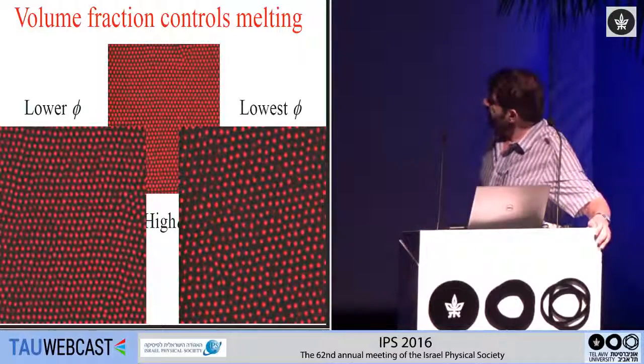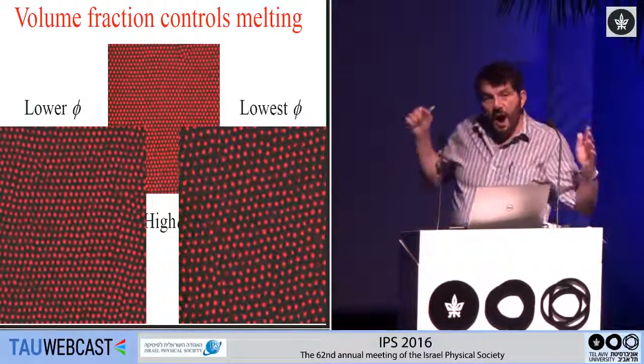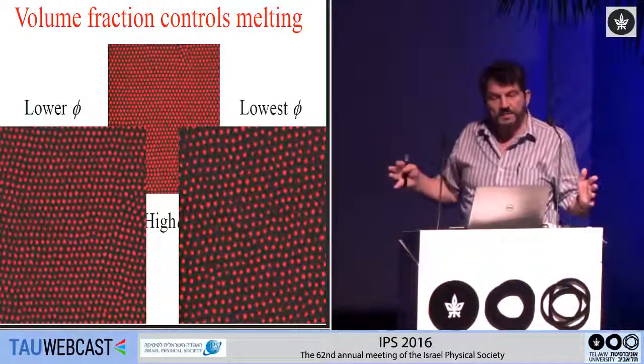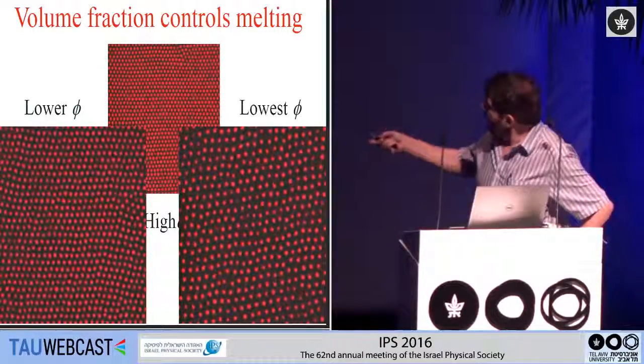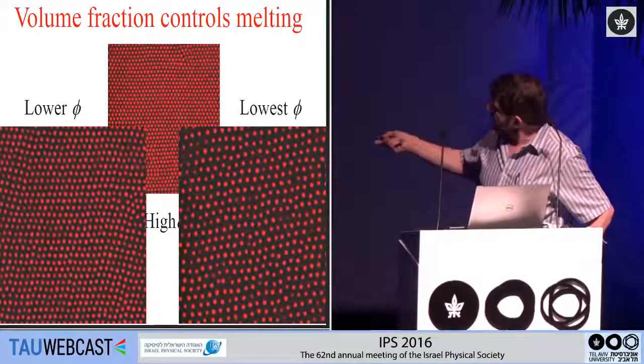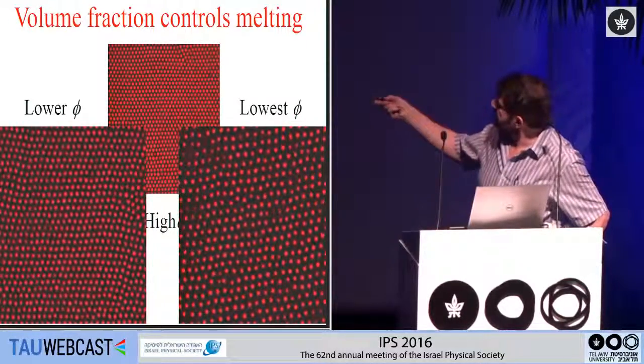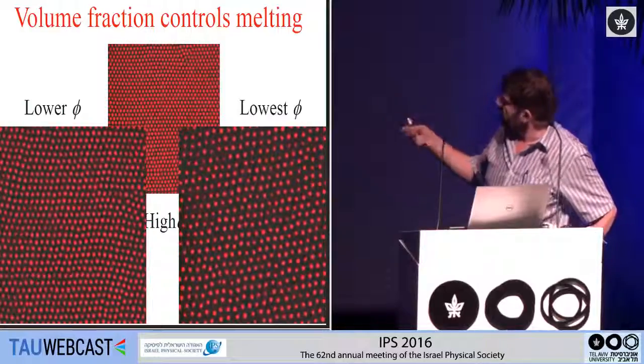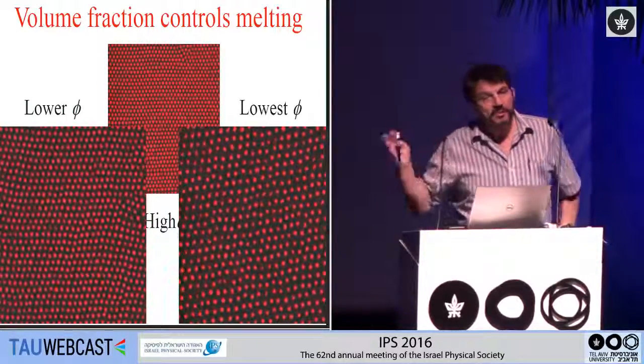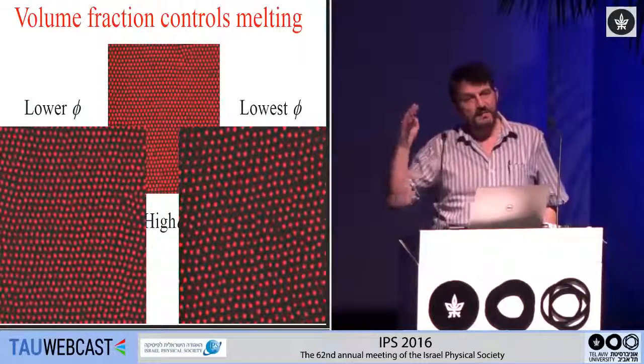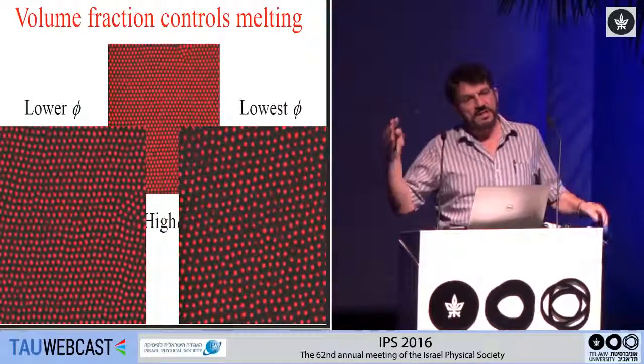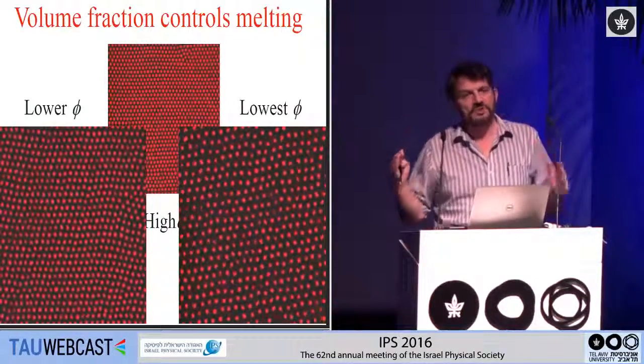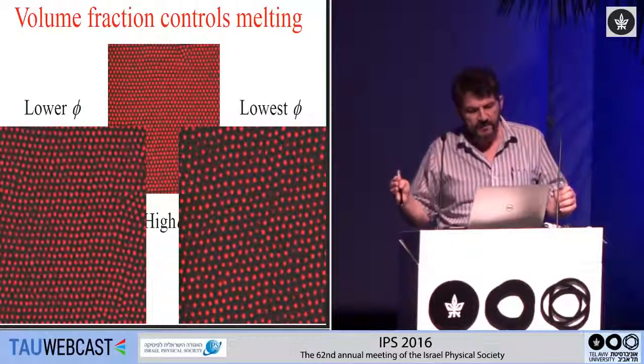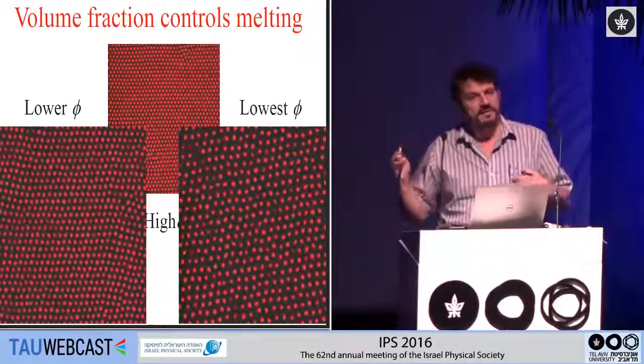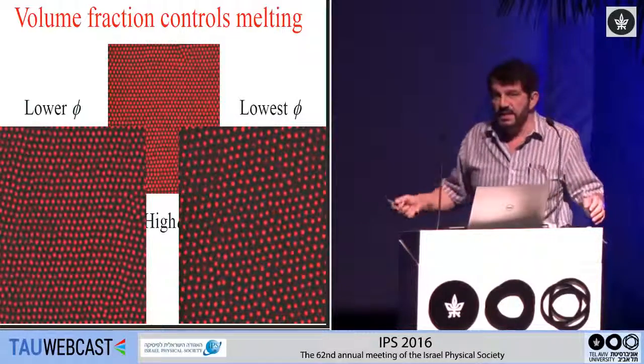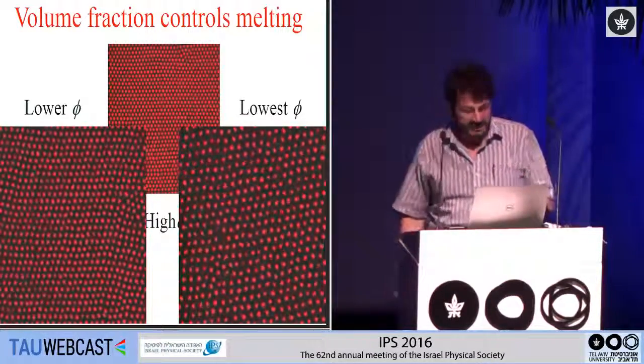And you can go even higher in temperature and lower in concentration. And now you see the particles are well separated. They're fluctuating an enormous amount. You can see some of them seem to go out of the plane of view that you're observing. But although they fluctuate, they remain in their symmetric positions in their crystal lattice. They can fluctuate a very, very large amount. Nevertheless, they're still crystalline. In fact, in this case, the lattice changes from FCC to BCC.